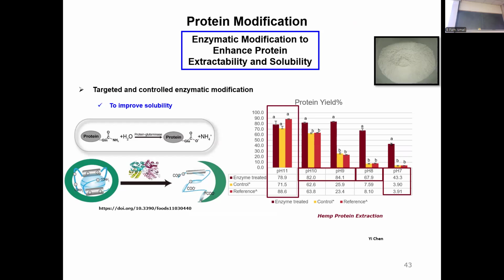And we use it to enhance protein extraction, and it also results in enhanced solubility. And we also work with hemp because hemp is very insoluble and hard to extract. You need pH 11 to extract the protein, which is really alkaline and causes color, off flavor, and ruins the protein. So we evaluated the enzyme at a reduced pH, and we were able to get an extraction close to 70% compared to only 8% of the protein extracted at pH 8 without the enzyme.